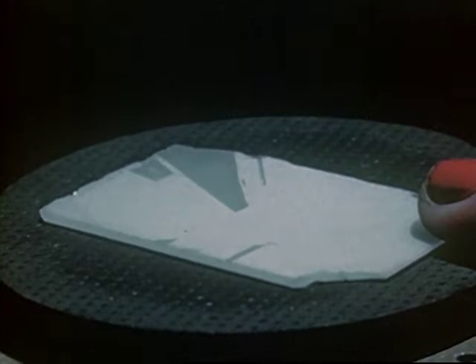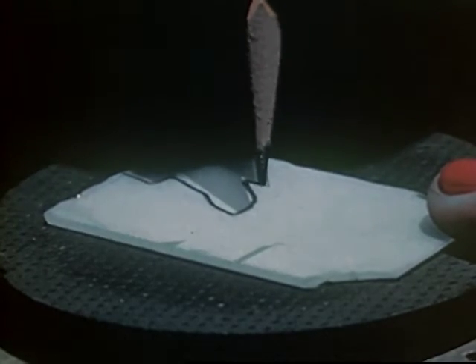Here are several examples of twinning as seen on etched wafers. The twinned portion is marked out with a pencil. When the wafer is being cut into quartz plates of the required size, the twinned portions will be avoided.